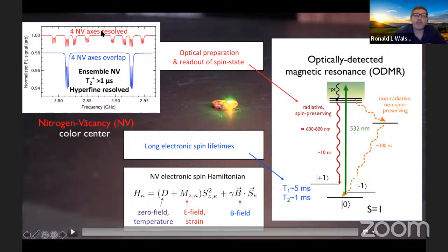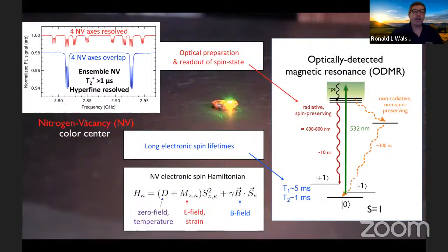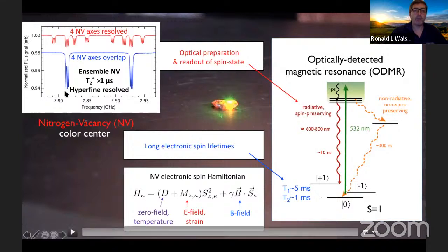Depending upon the direction of the static magnetic field that's applied, you can either have the four NV axes resolved, and their different ODMR splittings resolved because there are different vector projections along these axes, as shown in these four pairs above in red. Or you can have the projection of the static field be the same along the four NV axes, and then you get even better contrast, as shown in blue here, but you don't get the vector information because you're getting equal projection along all four axes, excuse me.